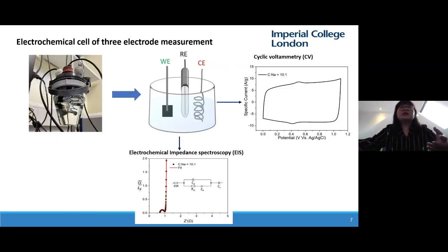Further investigate the mechanism to store the charge in the nanotube Bucky paper. I performed the electrochemical measurement of the electrode itself in a 3-electrode measurement first, before fabricating the device, to understand the mechanism between ions and electrode via cyclic voltammetry, and then to further investigate the internal resistance and charge transfer resistance by using electrochemical impedance spectroscopy.